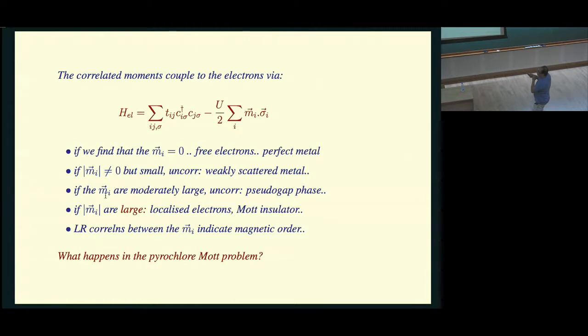If the moments are moderately large but uncorrelated, unordered if you wish, you end up with a pseudogap phase. It's sort of a much desired phase in many correlated electron systems. If the moments are large, which happens if the U is large, then you get a split band Mott phase. And of course, the correlations between the moments, or the structure factor that you find in the magnetic sector, indicates whether there is any magnetic order or not in the problem.